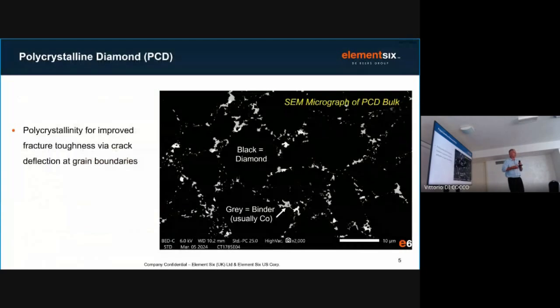So this is where we take a lot of single crystal diamond grains and sinter them together. So we're talking true diamond bonding. This is an SEM micrograph. So the black is the diamond grains, and the gray is the liquid phase binder between the grains. It's almost always cobalt based.